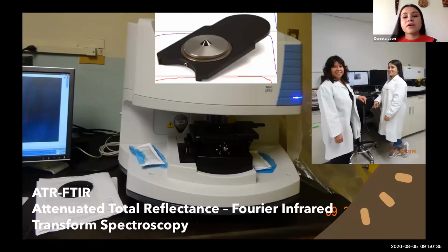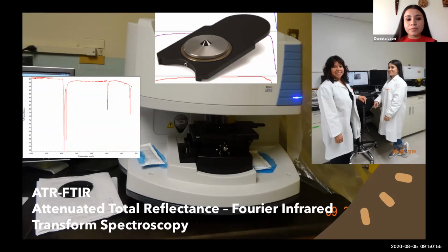So I use a crystal, a germanium crystal, through which some light will pass and penetrate the sample that has been placed on the slide. Once the sample receives the light, it will bounce back some infrared light to the detector. The detector will provide us a spectrum that we can use to compare to our library. The library will show us a percentage of match that we can use to identify the type of plastic.